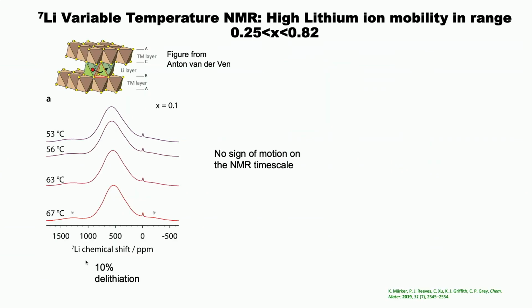And when NMR signals, so this is lithium NMR, so I'm looking at the local environment around the lithium, and when I pull out 10% of the structure, I see this very broad feature. I heat it up and not much happens.